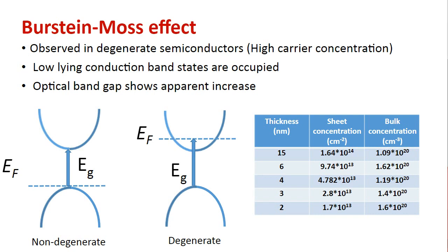Even though we call it a semiconductor, the number of carriers in bismuth selenide is really higher than in normal semiconductors. It's almost approaching that of a metal. So what happens is that the valence band is completely full, and some of the extra carriers go up and occupy the conduction band. Once that happens, the optical processes become a little more complicated.